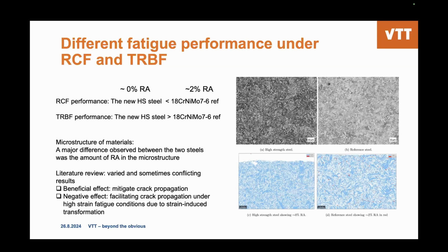And if we look at the literature review, sometimes we can get very conflicting results. The majority of work suggests the softer retained austenite has a beneficial effect for fatigue properties because it provides a lower stress level to mitigate crack propagation. But some works also suggest under high strain fatigue conditions, the strain-induced transformation of retained austenite to martensite could form a harder martensite phase, and the boundary could provide an easier path for crack propagation. Those are two schools we can see from the literature.